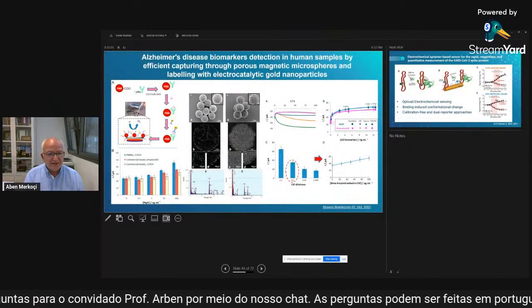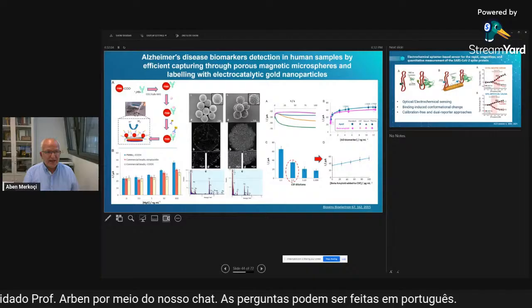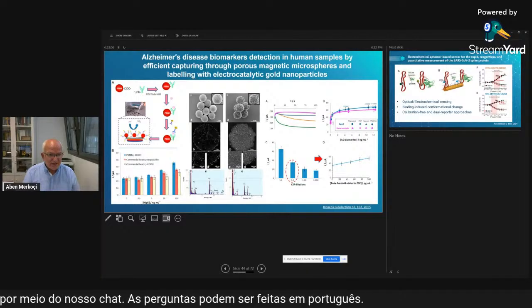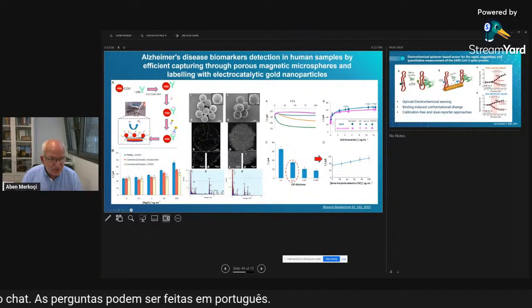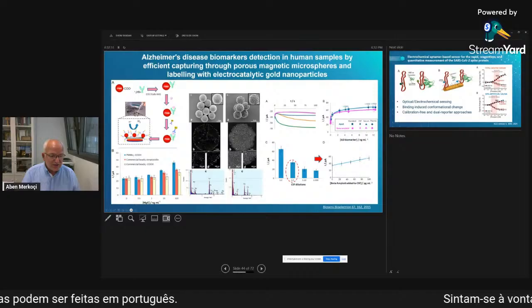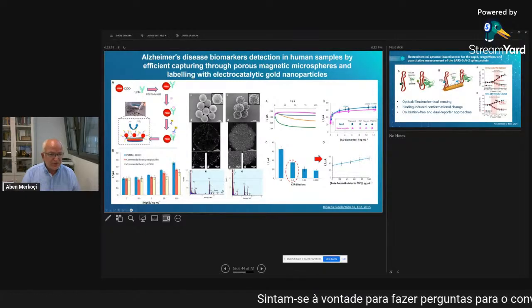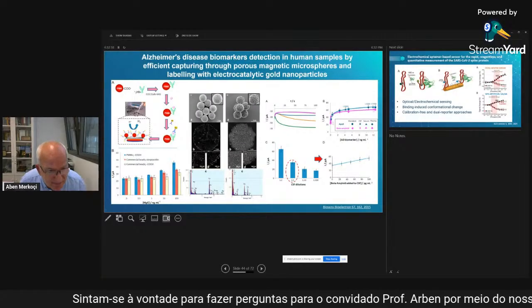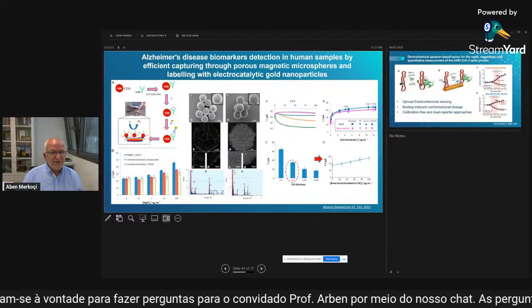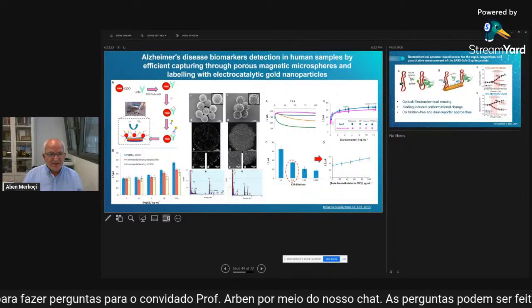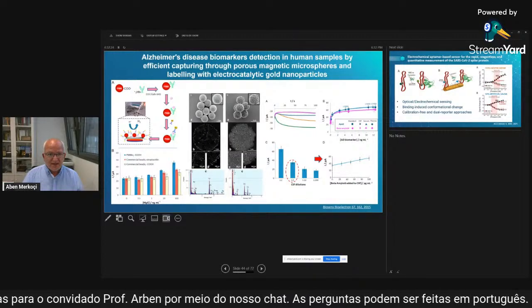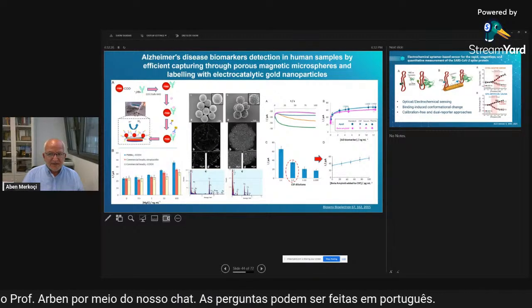First of all, a simple example in which we use the electrocatalytic system, in this case hydrogen evolution reaction, that is induced by gold nanoparticles. You know that gold nanoparticles are catalysts for hydrogen evolution reaction, and we use this detection system to detect some Alzheimer biomarkers with interest, for example, to detect this in human samples using magnetic microspheres.